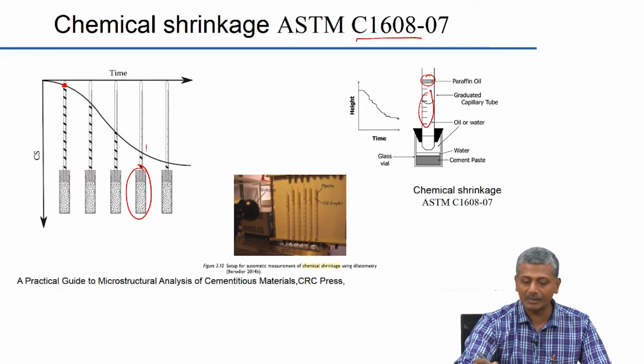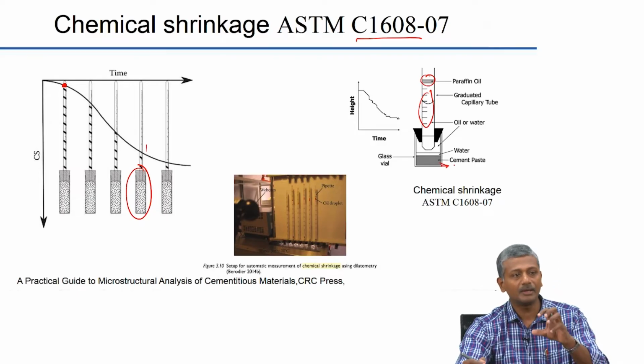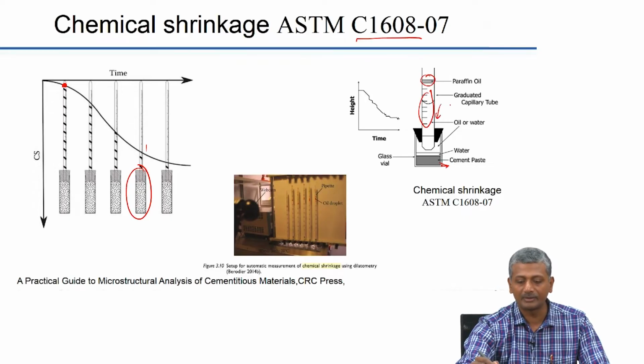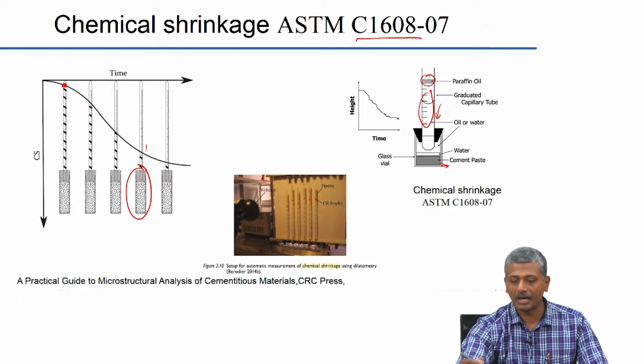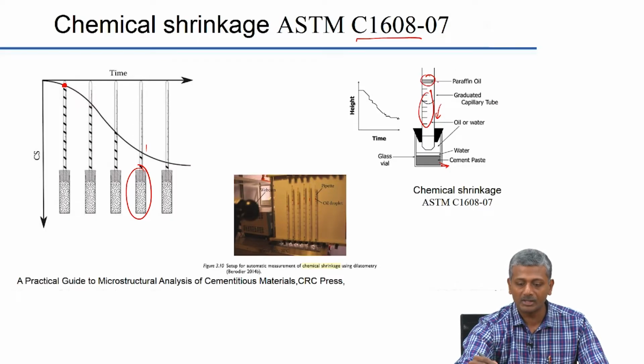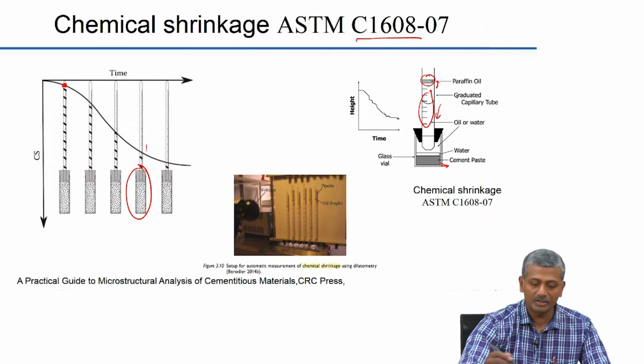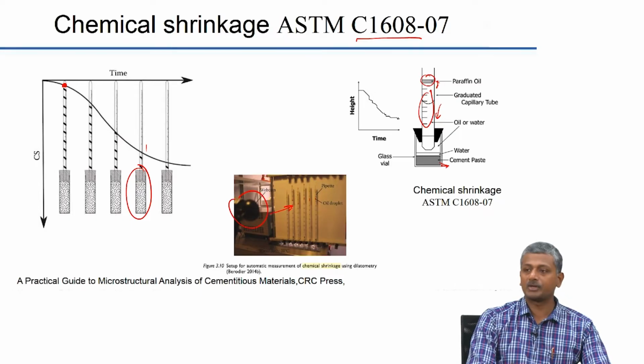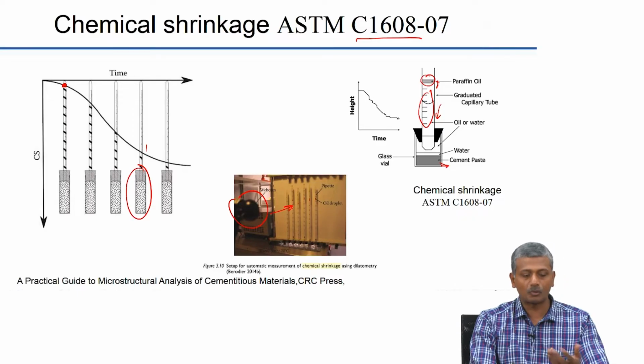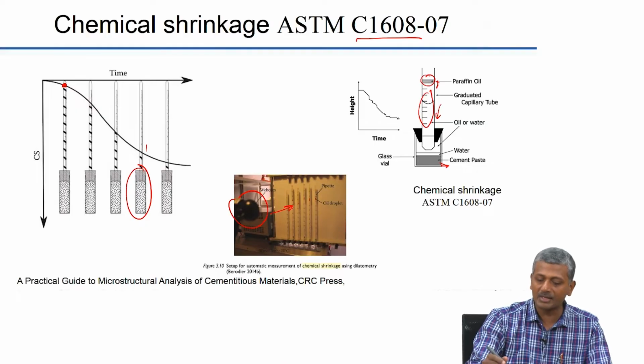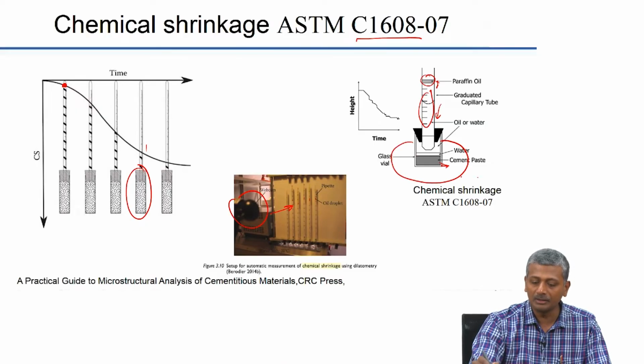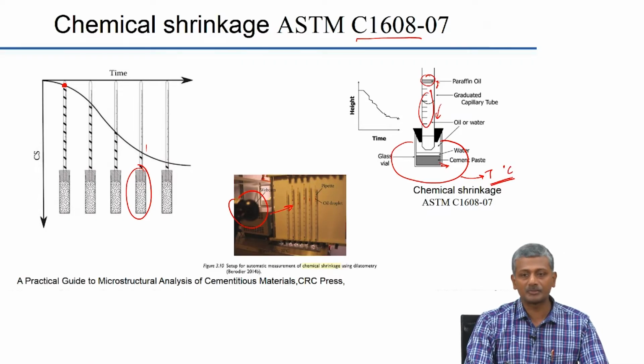Okay. So, what happens as chemical shrinkage happens in the cement paste, there will be some portion of that volume which will be filled up with this liquid which is here in the column. And because the paraffin oil at the top is not mixing with the liquid below, you can actually note that as the drop in height of the paraffin oil. And again, you can automate this process by setting up a webcam which can actually measure the chemical shrinkage directly. Okay. So, this is what people usually do to measure chemical shrinkage. It is not very difficult to set up, only thing it requires is that your cement paste should be in a temperature controlled chamber, because you do not want the temperature to be varying during the experiment.